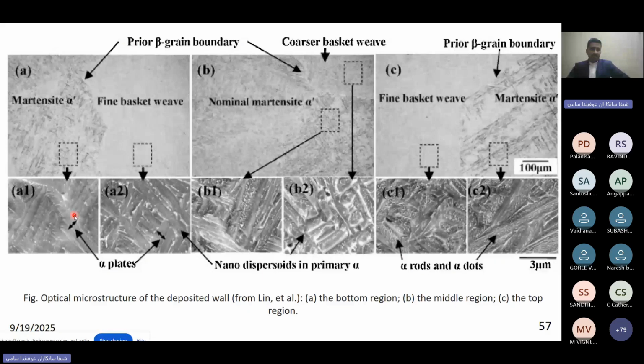For example, this is the titanium 6 aluminum 4 vanadium alloy after 3D printing by the WAAM technique. This is, I think, the bottom region. They observed a lamellar structure; you can see line by line, an alpha matrix structure. Then in some areas a fine basket-weave structure. Then this is, I think, the middle region, where again a lamellar matrix structure was observed, and again a fine basket weave, and then a matrix structure formed. So it depends upon distance. The structure is completely non-uniform. That is one of the challenges: the microstructure observed in the titanium 6 aluminum 4 vanadium alloy system. Okay, right.